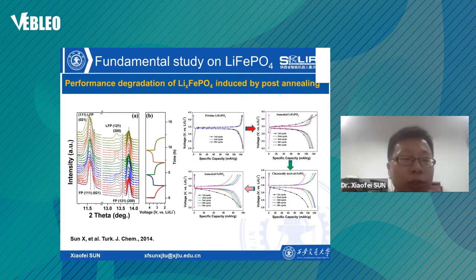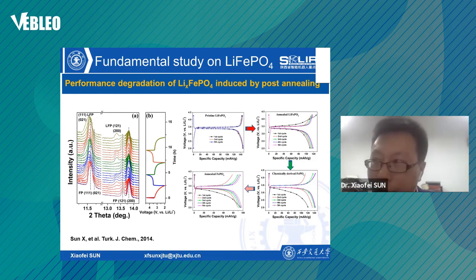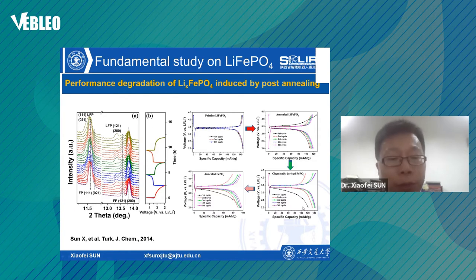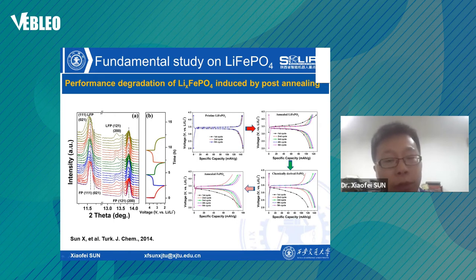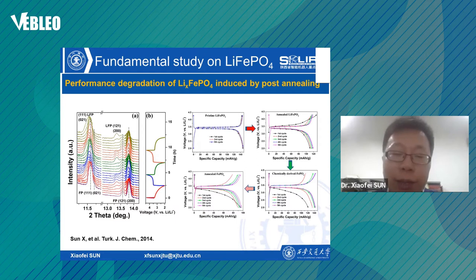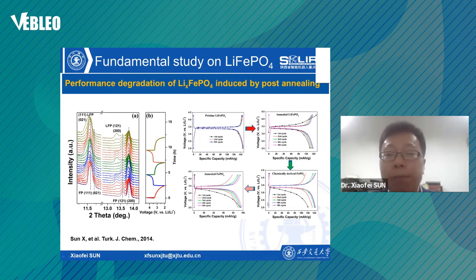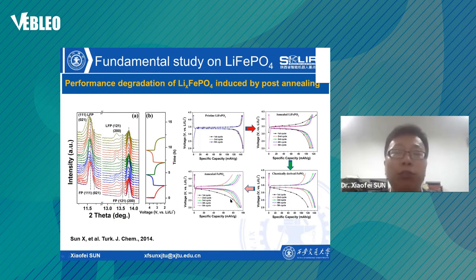We noticed that chemical delithiation in organic solvents is more reliable to keep the structure and morphology intact, comparing with chemical delithiation in aqueous solvents, and the mechanism is explained in this scheme. Post-annealing was then employed on large-particle lithium iron phosphate with different lithium contents, aiming to see the structure-performance relationship. With the help of in-situ synchrotron X-ray diffraction, a clear two-phase reaction during charge and discharge is observed, and the sluggish electrochemical kinetics is ascribed to the inferior battery performance of large-particle lithium iron phosphate.